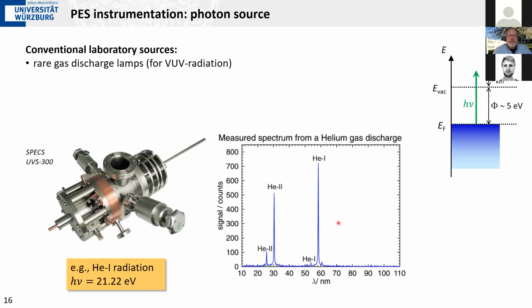Now it turns out the spectrum of this lamp is a little bit more complex. It does not just have a single line. The line that we are using mostly is this one here, helium-1 at 584 angstroms wavelength, or 21 eV photon energy. But there's a little bit more light coming out. You have some low energy satellites sitting at higher photon energies, or you have here helium-2 radiation, which comes from excited helium ions in the gas.